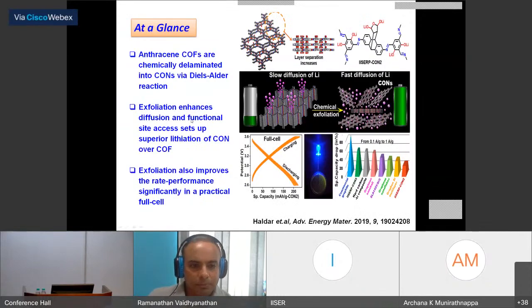So in principle, what we have achieved is we have used anthracene-based COFs and carried out a Diels-Alder reaction to make it into an exfoliated COF using this approach of a functionalizing exfoliation agent. By that, we have introduced additional functional groups to interact with the lithium, in addition to the functional groups already present in the COF. Also, the exfoliated structure gives the chance of introducing fast rate performance, which means fast charging batteries.